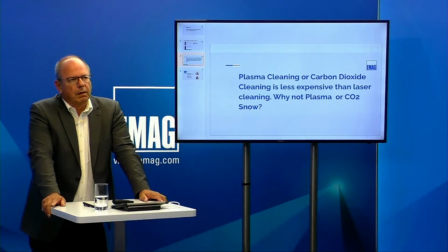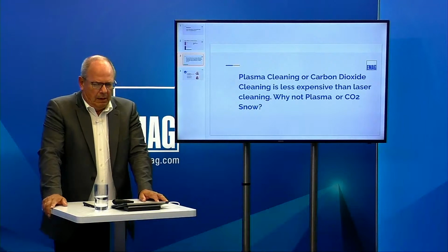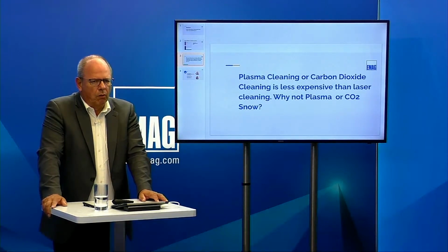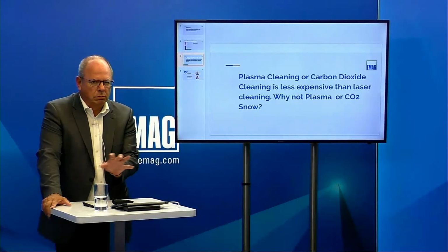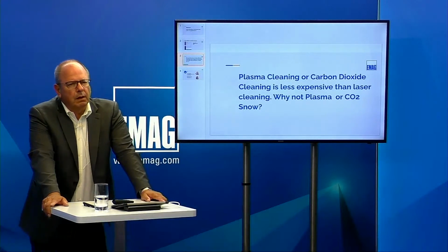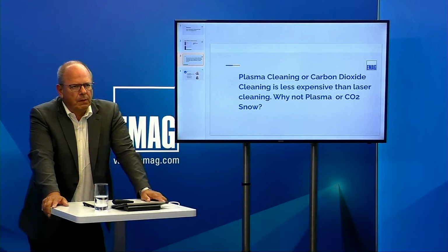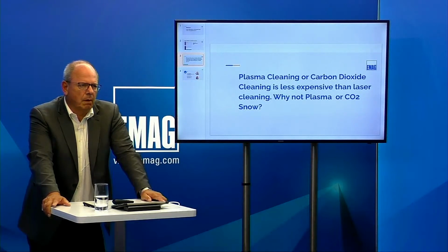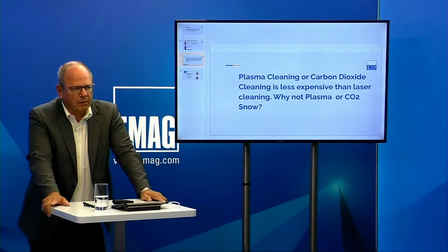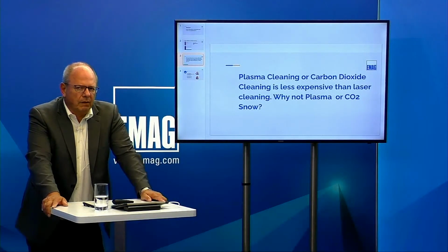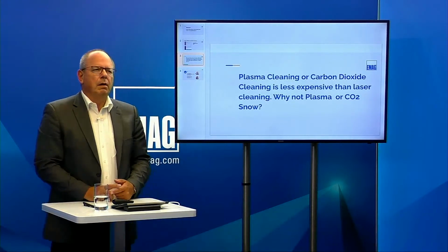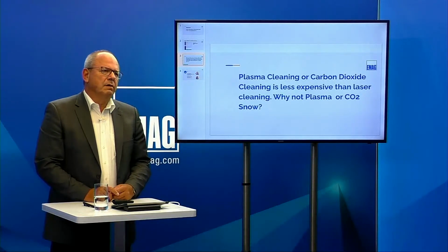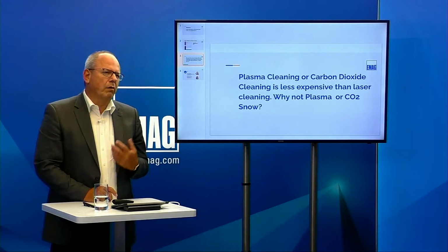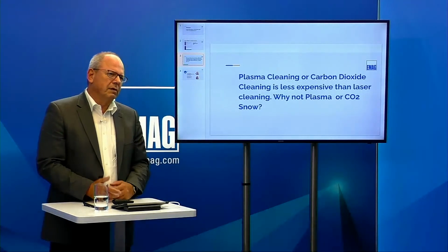Plasma cleaning uses a plasma jet to clean the surface. We looked at this process a while ago when we were deciding which route to follow. Plasma cleaning is very capable. It's relatively simple, and you can use it. It works very nice for example on an oil film or some corrosion inhibitors on a metallic part surface. This works pretty well. It doesn't work if you seek to remove oxides or any paintings. These are the limitations. The laser is more aggressive, and so the process has some limitations.